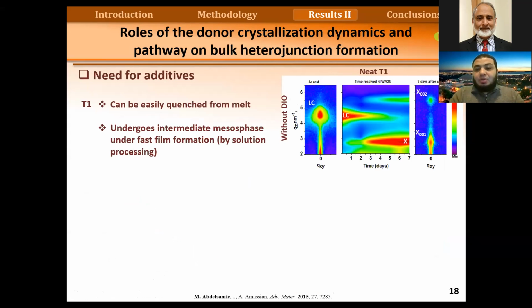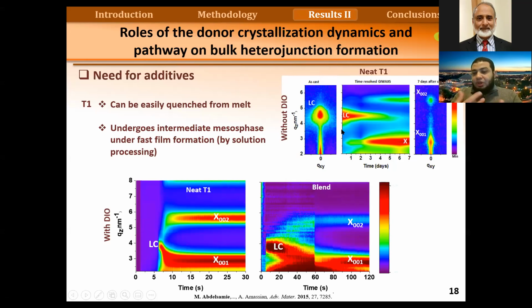So when we started initially with the material T1, what we found is that when we just cast it normally, it gets trapped into a weakly ordered liquid crystalline phase. With time, this phase, which is weakly ordered and has very low crystallinity, evolves over days into a highly crystalline phase. So we tried to use some additives to induce this in a shorter time, because we can't wait for days to process the material.